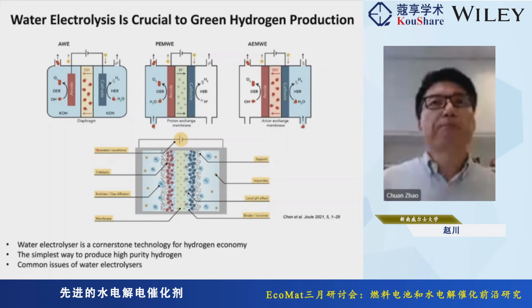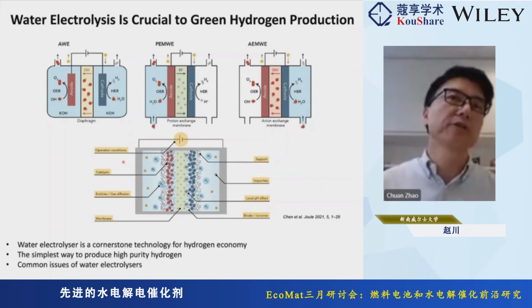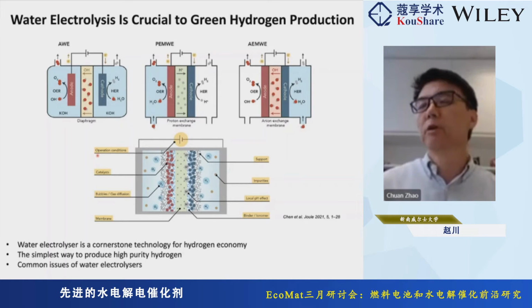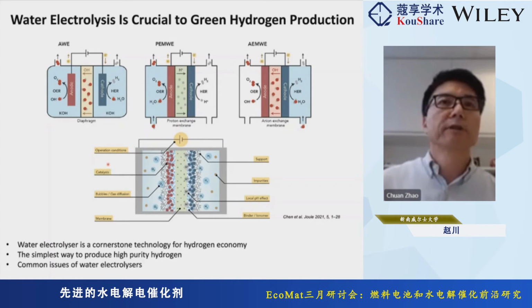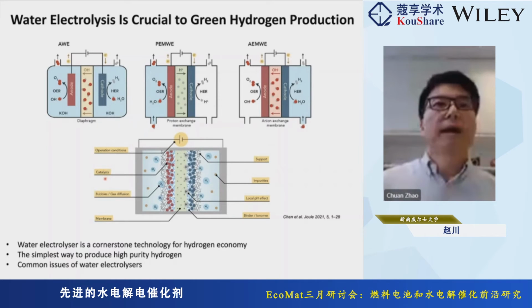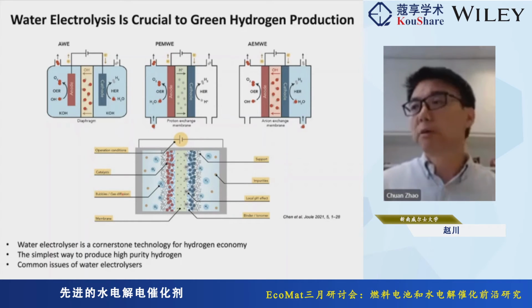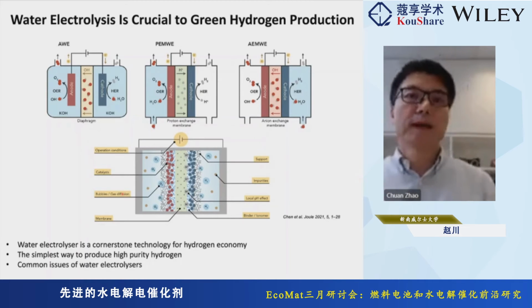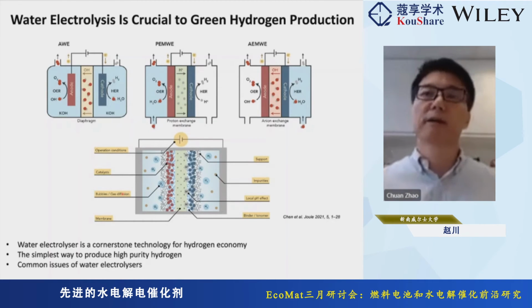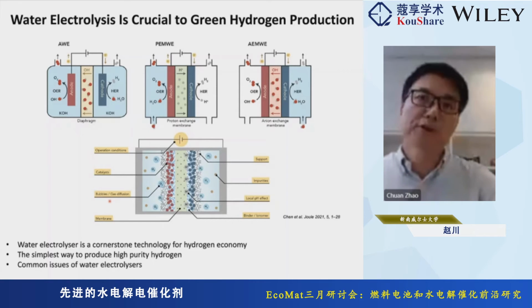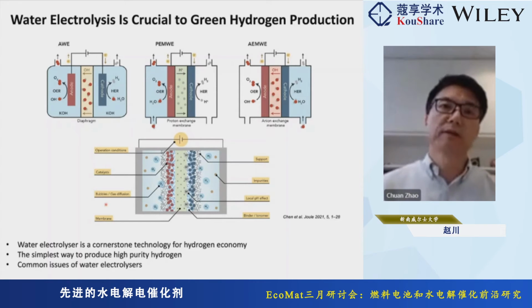So normally when we do the water electrolysis test, we work in a steady state standard condition in the lab, but in reality, the operation condition is very different. So we need to mimic those operation conditions to test our catalyst. And we also need a stable, active catalyst. And gas bubbles are a big problem. Water splitting, both anode and cathode, are gas evolving reactions, so gas bubbles are generally a big problem. I'll come back to that in a minute.